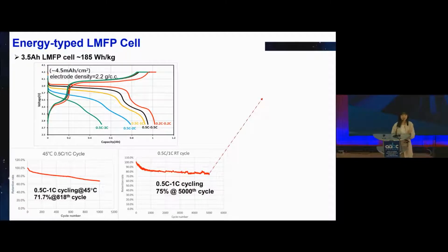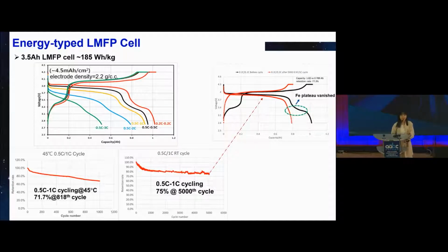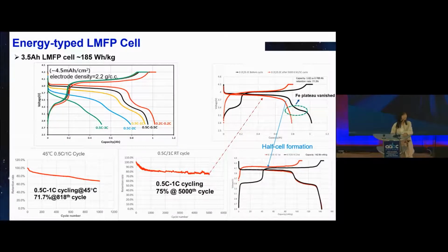However, after 5,000 cycles, we noticed the discharge curve of the cell revealed the disappearance of iron plateau. Therefore, to investigate the capacity fading mechanism, we disassembled the cell and took out the positive and negative electrode to conduct the so-called half cell formation. During the process, we observed the appearance of iron plateau, and the capacity of the material returned to over 95%. This indicated that the disappearance of iron plateau was due to the lithium depletion. So this means that maybe in the future, we may recycle the LMFP by replenishing lithium to the material. In addition, the ICP analysis of the anode electrode also shows the presence of 310 ppm manganese in the graphite anode.